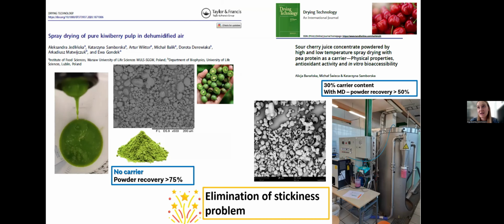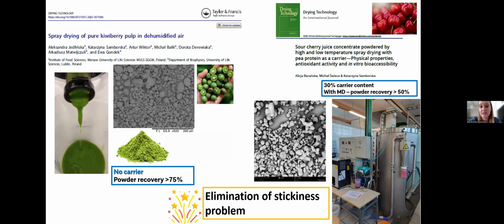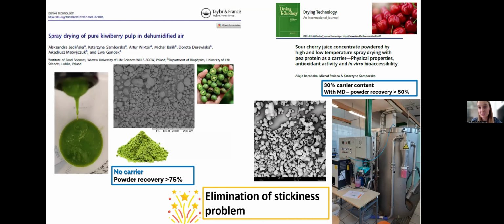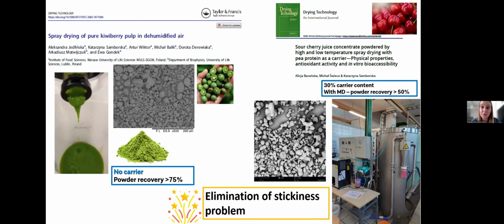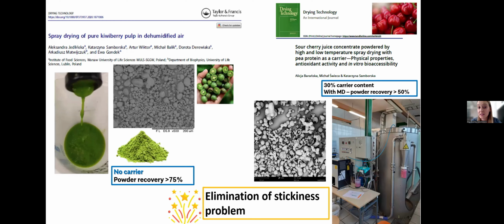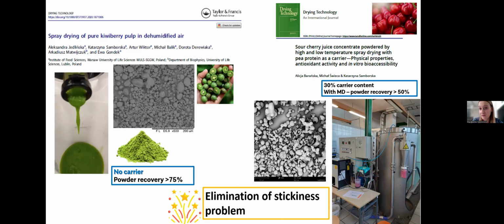Continuing with our work, the idea of eliminating the carrier completely appeared. So the first study that was performed with no carrier was pure kiwi berry pulp, which was spray dried using, in comparison, traditional spray drying using high temperatures, and as well the dehumidified air assisted spray drying. Due to the composition of the materials, because, as I will show you in a second, sometimes it is possible to reduce the carrier completely, but sometimes not. It really depends on the material's composition. Here, due to the high content of pectins in the kiwi berry pulp, it was possible to eliminate the carrier completely. And at the same time, as you can see, with no carrier, due to air dehumidification and due to low drying temperature, we noted very high powder recovery, over 75%.